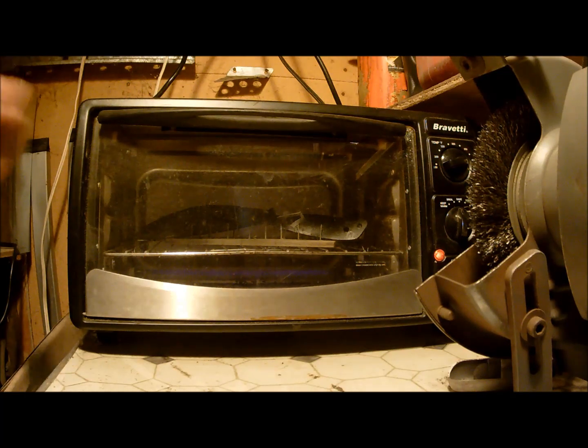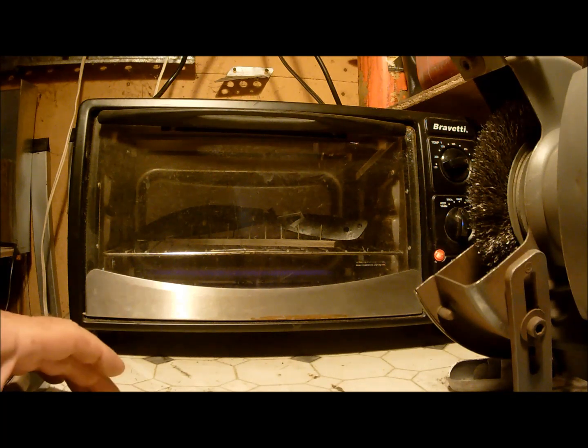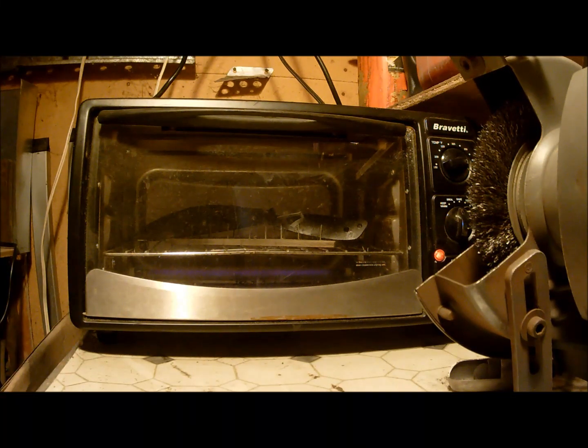hours. This particular steel, this spring steel, which is almost certainly 5160 spring steel, wants to get forged at about 16 to 1800 degrees. It wants to get heat treated at about 1525 degrees when you quench it, and then it wants to get tempered at between 375 and 400 basically. So I've got this set at 400. Those temperatures for this particular steel will give it its maximum strength, maximum durability, and still make it a good sharpening steel.